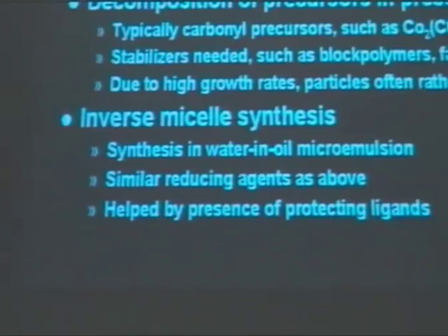The third technique I want to show basically uses components of the previous ones, which is the synthesis in inverse micelles. You can stabilize water in oil or oil in water emulsions by using surfactants. And by doing that, we take the example of a water in oil emulsion. You have tiny little water droplets of sizes of maybe 10, 20, 50 nanometers, which are stabilized by a layer of surfactant molecules in an oil phase. And these systems are basically stable.